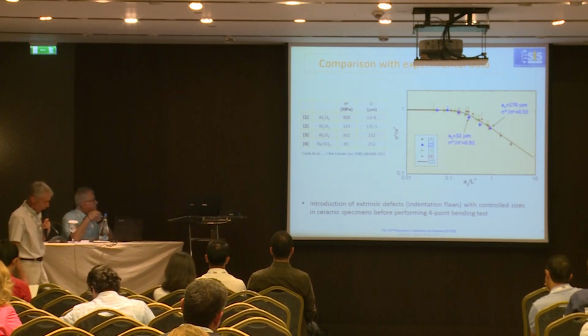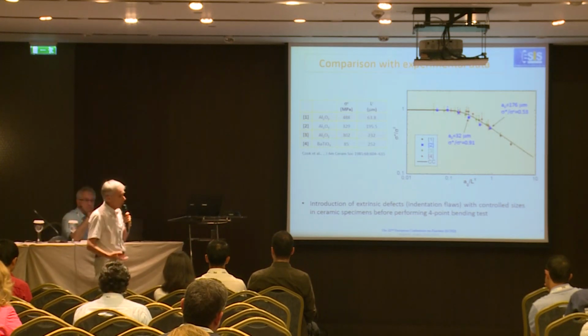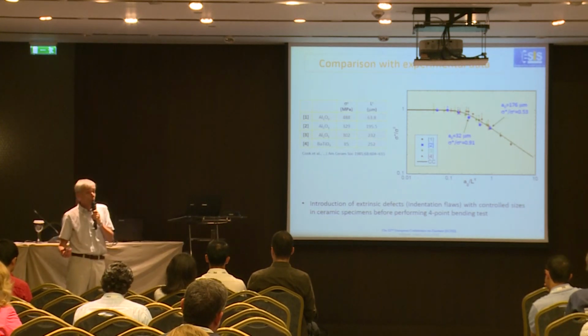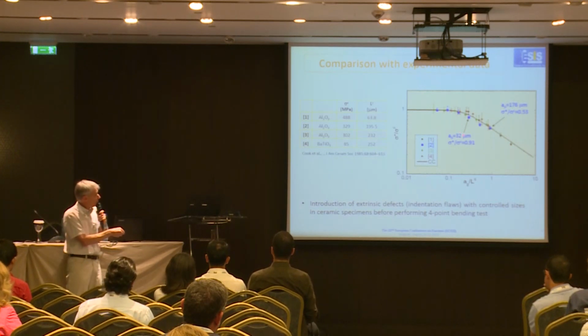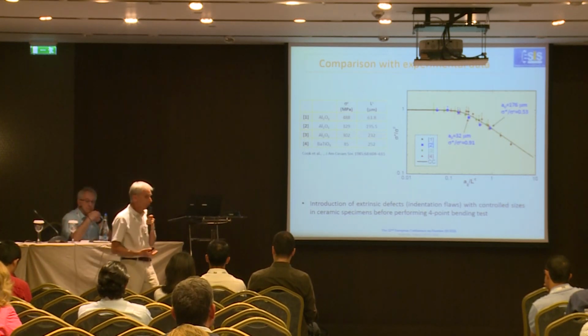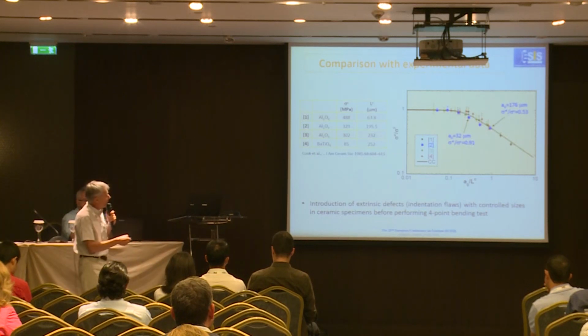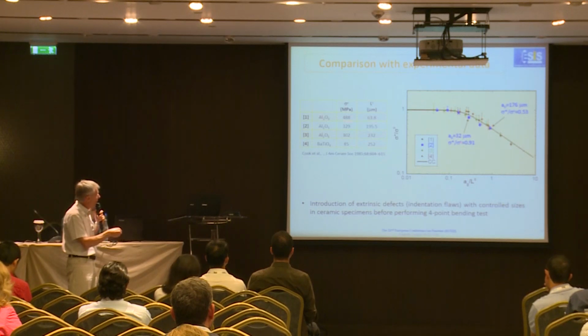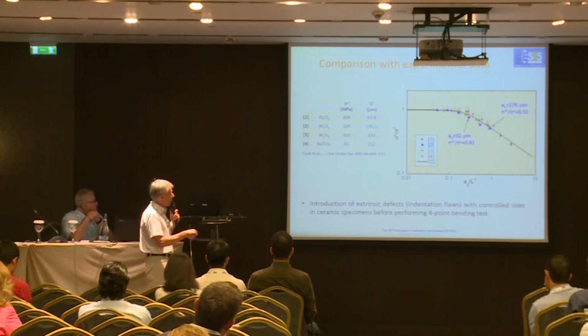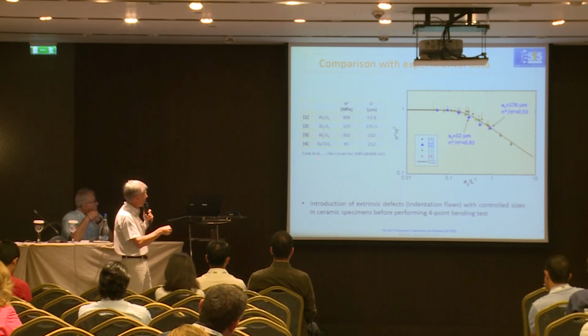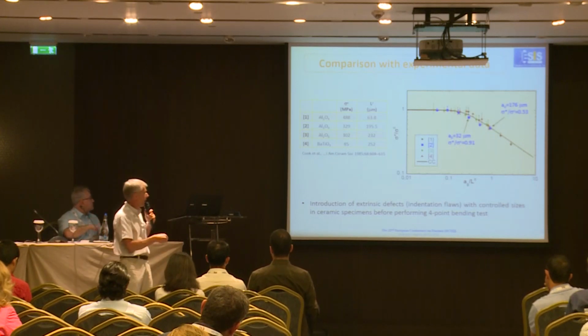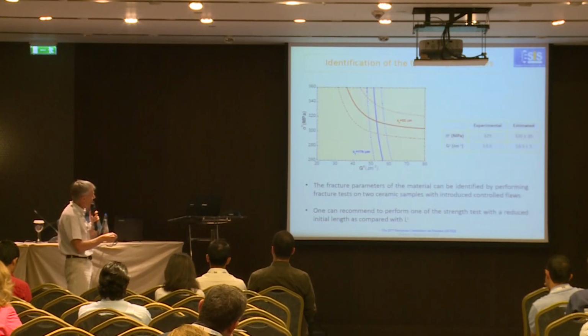Okay, so one question may arise. Is it possible to use some experimental data to extract the fracture parameters GC and sigma C? So this is what I tried to do. I have selected 2 points here from this kind of alumina, and I use the strengths given by Cook and Hall to have this graph,